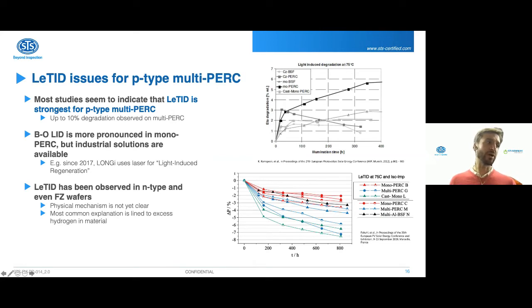And you may say, okay, but mono still has the traditional historical boron oxygen LID issue, which is very pronounced in mono PERC. It's more pronounced than in multi. Yes, that is true. However, there has been some industrial solutions which are now available and that we see in the factories to remove this light-induced degradation phenomenon.